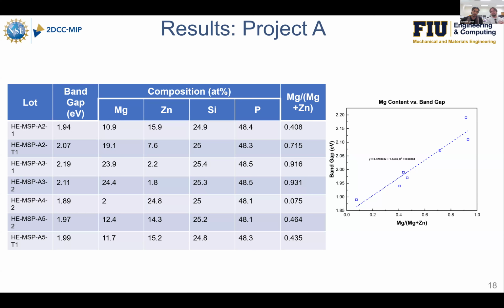I should have mentioned before, UV-vis was taken after polishing the samples, and some of these crystals obviously don't survive the polishing step because they're either too small or they damage very easily, or they're just too small to provide any valid data that could be reported.